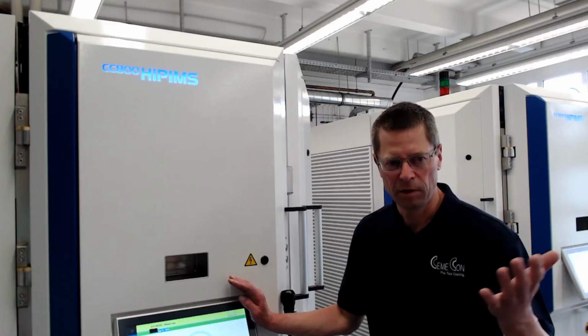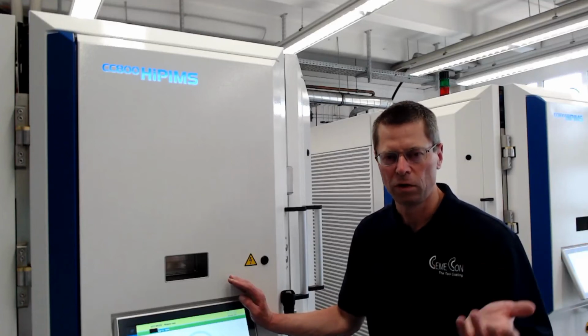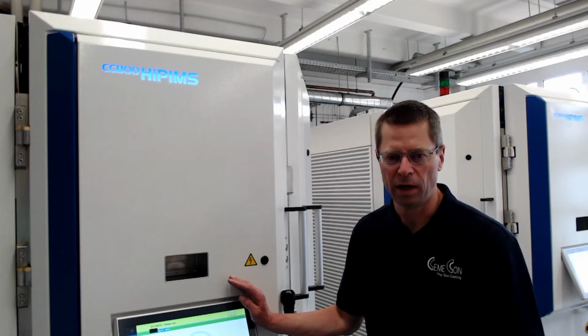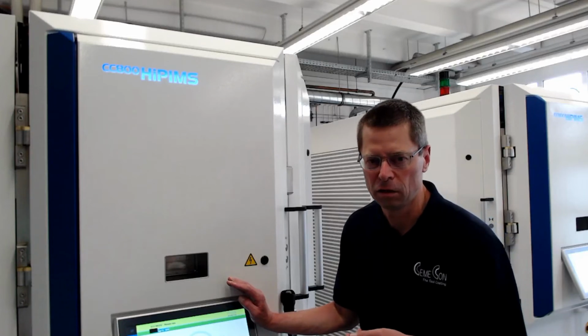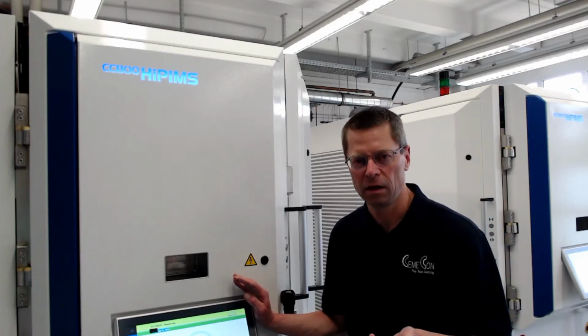For example, adapting back to your question before, when you have tools which have, after regrinding, let's say, a small deficit in the surface, makes the coating probably half a micron thinner. In the final end, the product will be better because of better adhesion on the old surface. So yes, it's easy to change them. And to make it even easier for you, we have a fully open target concept, so you can run your targets for your product, your composition, and you can utilize the full power of sputtering. That's a full table of periodic table of elements can be applied to the coating chemistry.